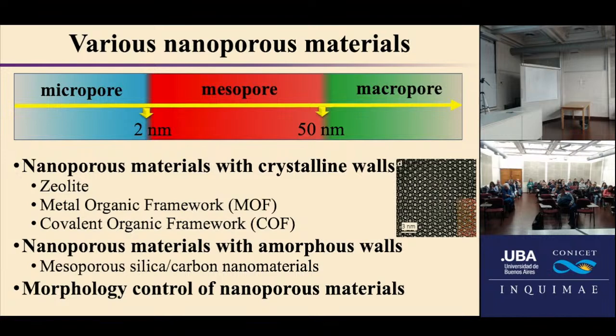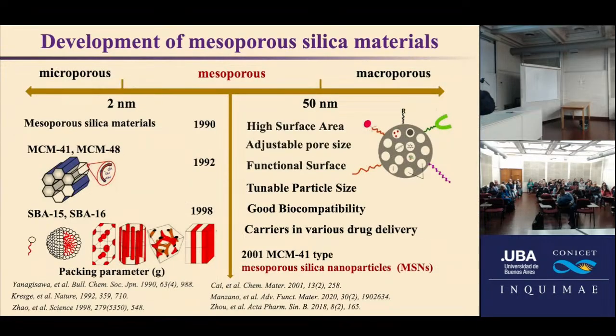So why nanoporous materials? We know nanoporous materials include microporous materials, with pore size smaller than 2 nanometers, mesoporous materials, with pore size between 2 and 50 nanometers, and macroporous materials larger than 50 nanometers. So there are different types of nanoporous materials, including, for example, zeolites with crystalline walls, of course. This type of materials includes MOFs and COFs, and also nanoporous materials with amorphous walls, such as mesoporous materials like silica, carbon nanomaterials, etc. And also, it's a hot topic to have the morphology control of nanoporous materials, especially with the nanostructure or the morphology well defined. There's a reason for that. I will mention it later on.